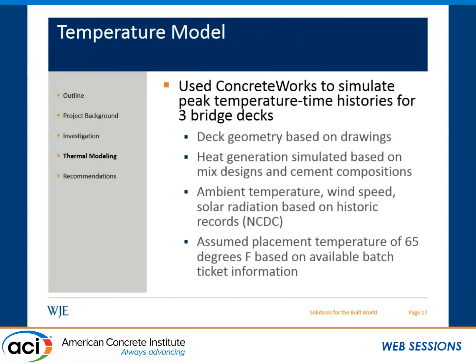In our temperature model, we used Concrete Works to simulate peak temperature versus time histories for 3 of the bridge decks we looked at. We took the deck geometry based on the bridge drawings, and we estimated or simulated the heat generation in the concrete due to hydration based on the mix designs and cement compositions that we were provided by the DOT. We took records of ambient temperature, wind speed, and solar radiation and actually input them into the model. And these records came from the National Climatic Data Center. And we assumed a placement temperature of 65 degrees for all of the concrete batches, which was based on limited batch ticket information that was available to us.